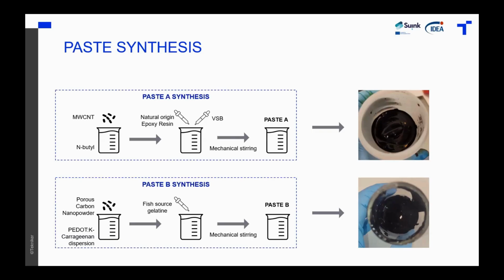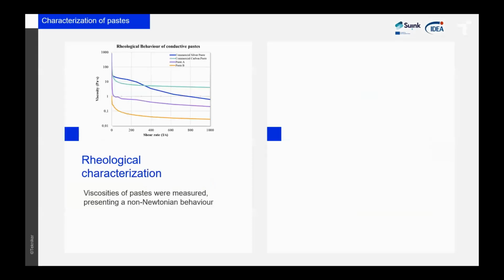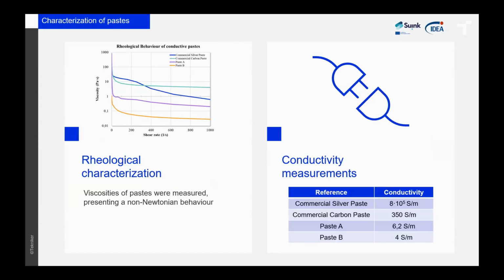After this, we decided to make a rheological characterization, not only of these two pastes, but also of two commercial ones, one made of silver and another one made of carbon. As we could see in the image, the four pastes have a non-Newtonian behavior, so it's okay for printing them by screen printing. We also made the conductivity measurements, and it's true that Tekniker's developed inks do not have as much conductivity as commercial ones have, but this doesn't mean that they couldn't be used in our temperature sensors.